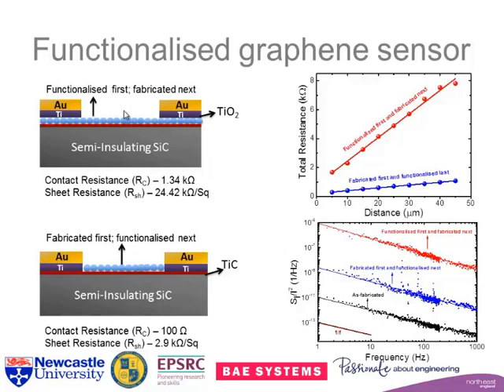The first one, favored by the materials people who grow it, is we grow the graphene, we then functionalize it, and they give it to the sensor people. Well, that doesn't really work, because when we put the contacts down, we form titanium dioxide, and the titanium dioxide here gives us a much higher resistance, so functionalized first, fabricated next. So these are TLM plots, and it also gives us far higher noise.